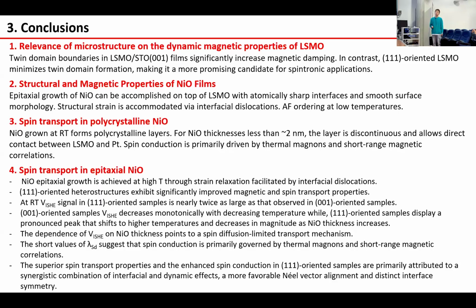For NiO thickness less than 2 nanometers, the layer is discontinuous and allows direct contact between LSMO and platinum, and the spin conduction is primarily driven by thermal magnons and short-range magnetic correlations. And finally, we studied the spin transport in the epitaxial NiO, where epitaxial growth is achieved at high temperature through strain relief relaxation facilitated by interfacial dislocations.